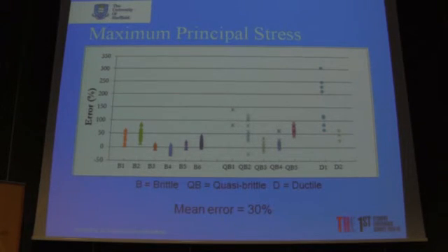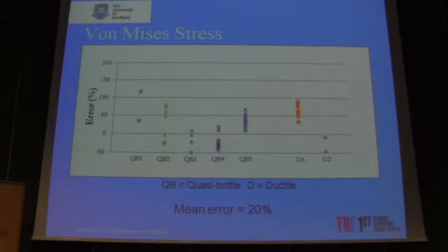exceed -27%. To counteract the apparent increase in scatter and non-conservatism, von Mises stresses were used as the assessment stress, which resulted in less scatter but slightly more non-conservative results.